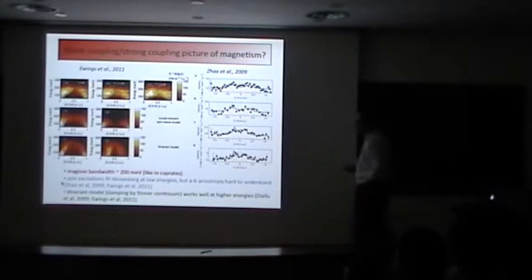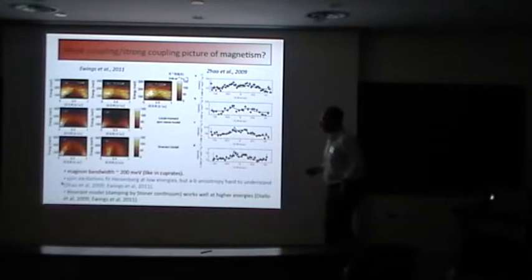Okay, so here's some recent neutron scattering measurements from Ewings et al., posted just a little while ago. Here is the dispersion of neutron scattering, showing spectral weight extending out to about 200 or so millielectron volts, meaning the single magnon bandwidth may be up to 200 millielectron volts.